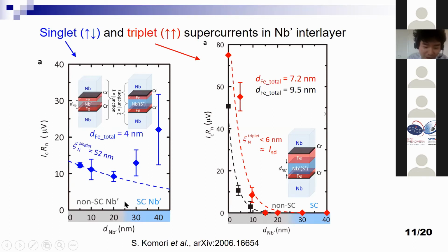When this niobium interlayer is thinner than 25 nanometers, it doesn't become superconducting, so it's normal state niobium. In this region, if we increase the thickness of this niobium interlayer, singlet supercurrent slowly decreases. So it shows a very slow decay. That is simply because the non-superconducting barrier is becoming thicker. But once the interlayer becomes superconducting, we can observe a significant enhancement of this supercurrent.